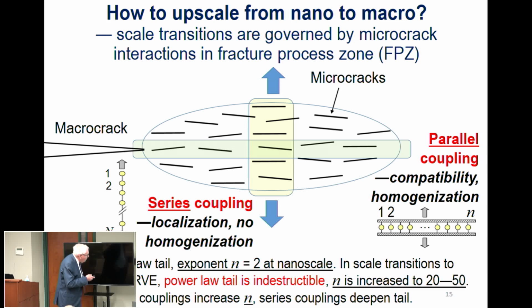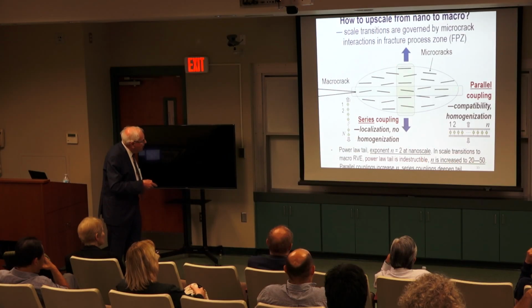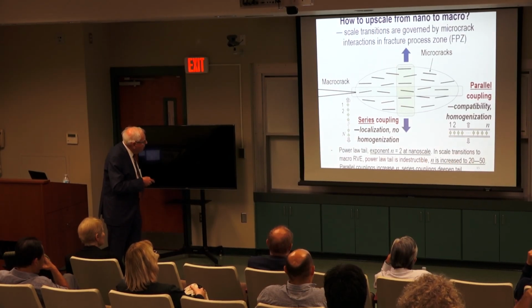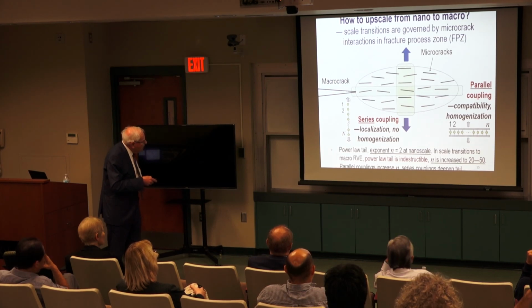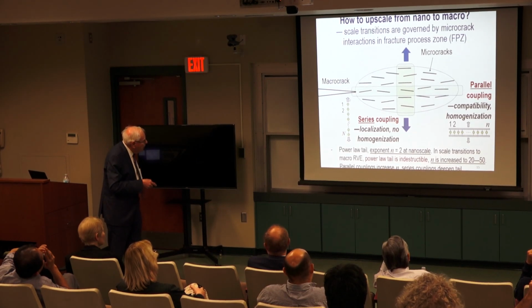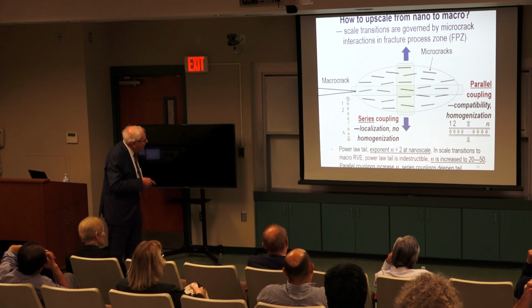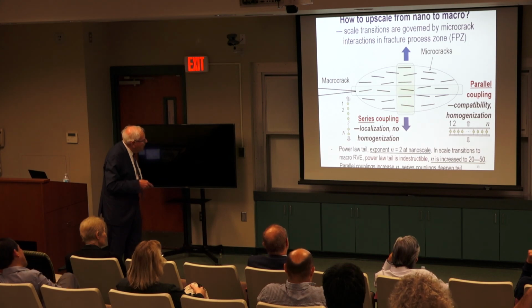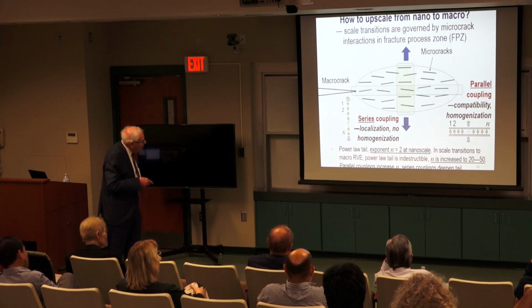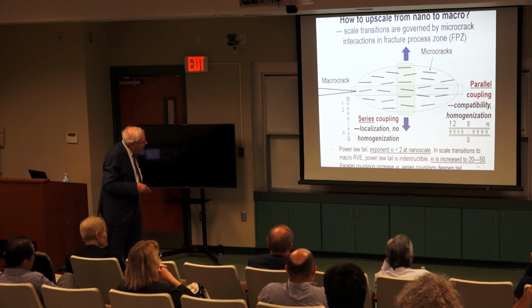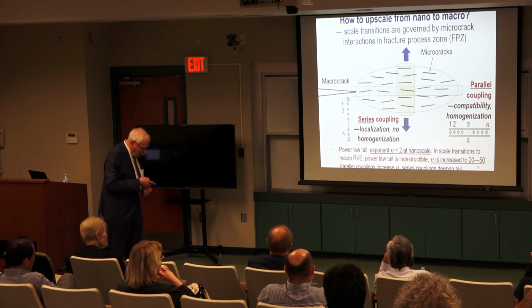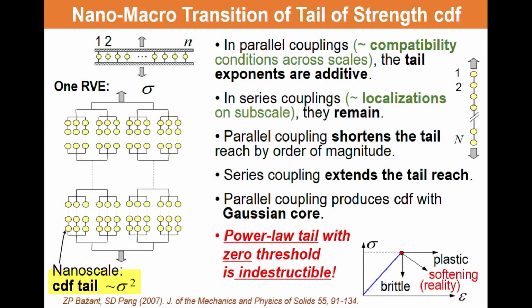And the failure or propagation then requires what? So you can imagine a process zone where there is already a formed open microcrack. Microcracks are obviously mostly aligned in mode 1 loading, and they have a tendency to localize, so that acts like a chain, if they always localize to failure at one point. And there are some other microcracks which are constrained laterally by compatibility condition, and that behaves like a fiber bundle. All right, now we work on this, consider some models which give this transition.